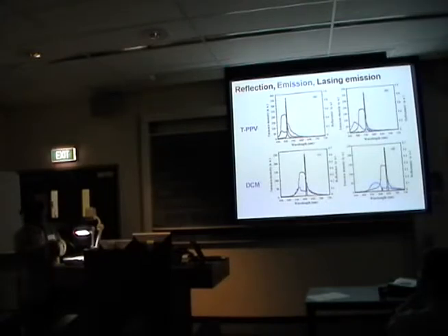However, if we make the cholesteric liquid crystal with a longer pitch, the higher energy edge is located near the emission peak in both cases, but still lasing occurs at the low energy edge. So lasing always occurs at the lower energy side of the photonic band.